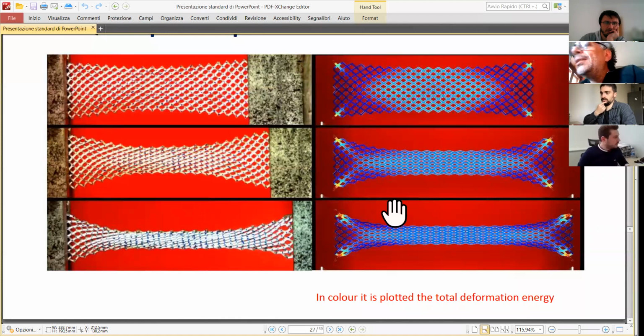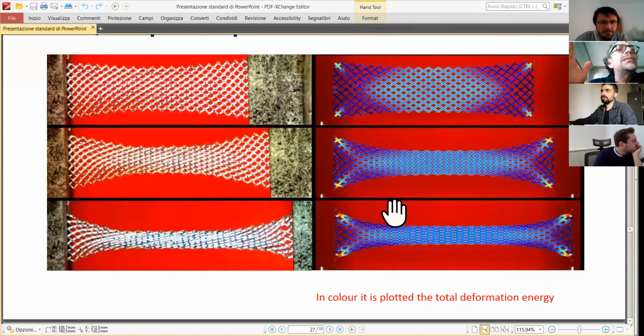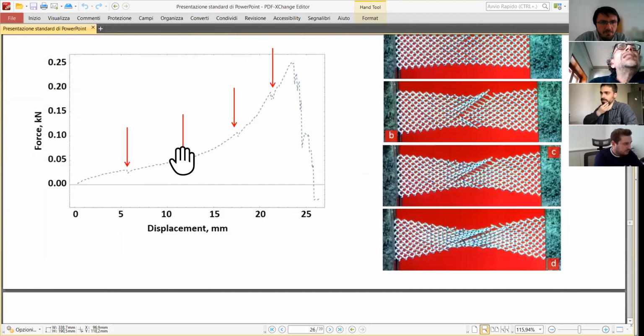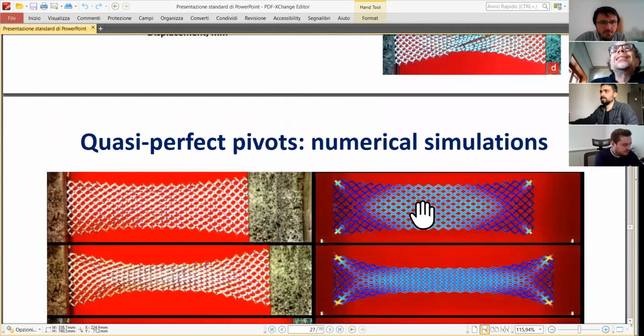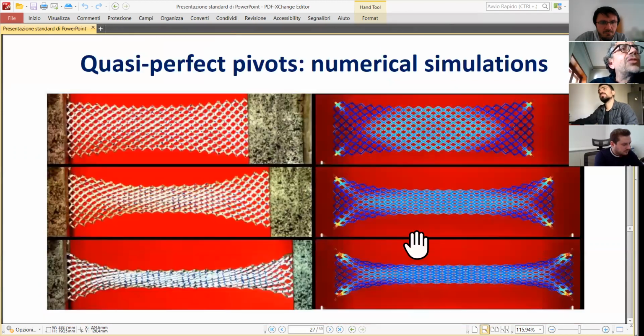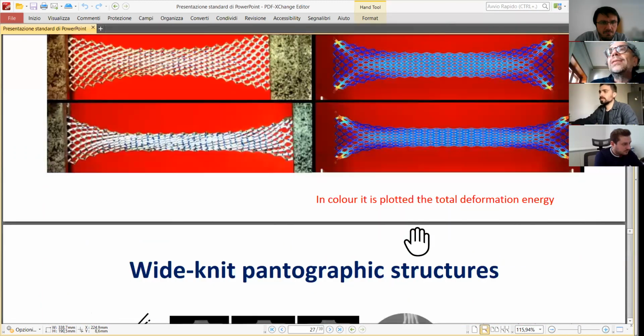I hope that you allow me 2 minutes of philosophical considerations, only 2 minutes. Without a theory, you cannot design experiments. We could design this metamaterial simply because we had a very careful mathematical model and very good numerical simulations, which allowed us to forecast the behavior of the specimens which we were going to build. Of course, if in the building you have defects, then you get a different behavior, okay? It is rather difficult to get such a well-ordered microstructure, but actually we are succeeding in this.